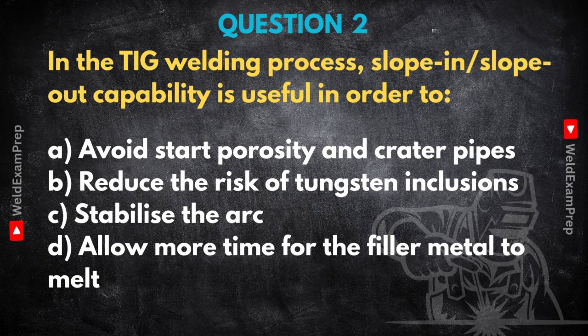Got it. The answer we're looking for is A, avoid start porosity and crater pipes. And this is where those seemingly small machine settings become really important for the final quality. Slope-in and slope-out are basically just current ramping functions, managing the heat. Slope-in is that gradual increase in current right at the start. If you just hit it with full power instantly, you risk porosity, little gas bubbles getting trapped, or even thermal shock. Slope-in lets the weld pool establish itself nice and smoothly, and then slope-out does just the opposite at the end. It's a controlled, gradual decrease in current.